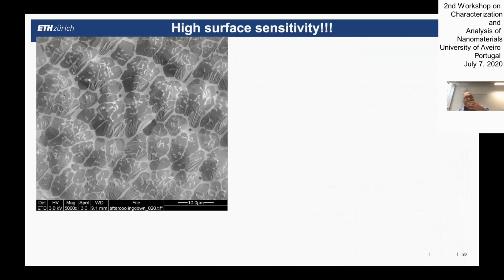Yeah, and then just one final example on this, and then I'll stop with SEM, is the surface sensitivity was even higher than that. So I showed you we can see single layers of graphene. And here on the left side, you see graphene grown on copper. You see these dark islands as graphene on copper.